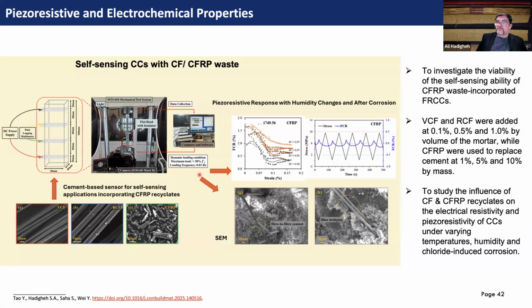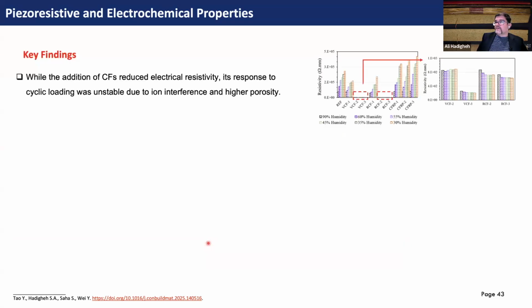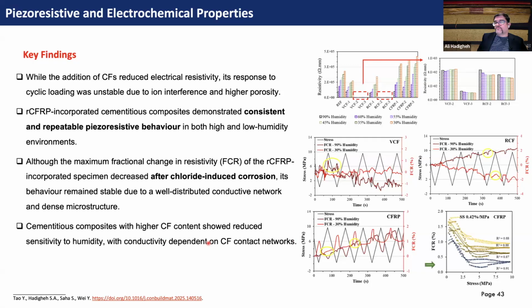and incorporated these concretes into those samples and tested them, and we found out that the response of those samples with carbon fiber in them and recycled carbon fiber wasn't really stable. So it wasn't very good for self-sensing. Piezoresistivity wasn't stable. But those with CFRP basically had a better performance, a kind of continuous and stable performance. That's something that we can manipulate and get self-sensing